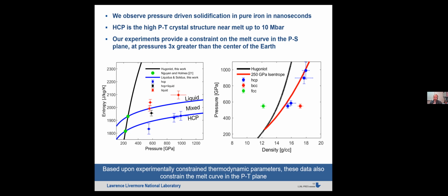No, so actually we did account for that. I am presenting the final entropies. I am not presenting the entropies on the shock state because I accounted for heating due to the X-ray ablation plasma and heating due to the concurrent heating of the X-ray light source. So there are two excess sources of entropy I've accounted for, and I've systematically added those corrections into the entropy states.